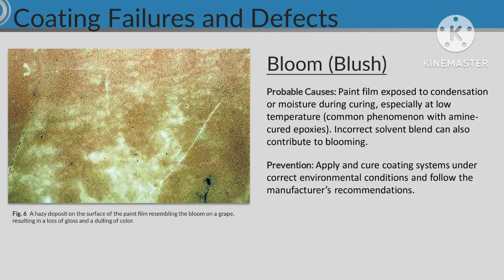Bloom / Blush. Probable causes: paint film exposed to condensation or moisture during curing, especially at low temperature; a common phenomenon with amine cured epoxies. Incorrect solvent blend can also contribute to blooming. Prevention: apply and cure coating systems under correct environmental conditions and follow the manufacturer's recommendations.